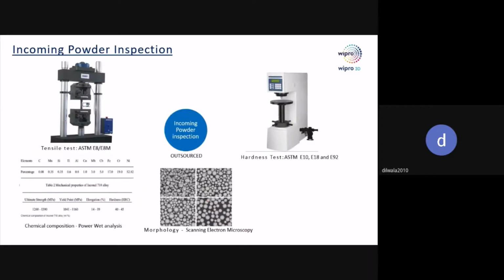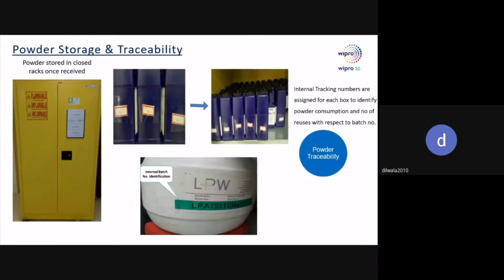Then we do tensile tests of coupons which have been printed from this powder. Then we do hardness testing also on the coupons which have been printed using that powder. Then this is the microscopy morphology images seen by SEM, which is scanning electron microscopy. Once all of these are done and all are meeting the requirements, then we accept the powder.